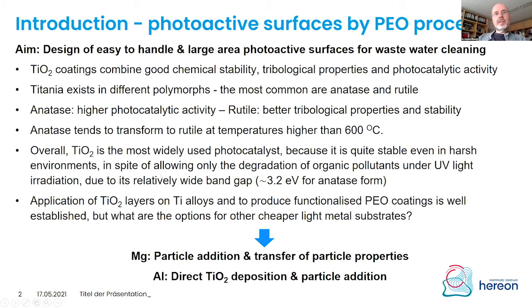So overall, one can say that titanium dioxide is probably the most widely used photocatalyst, because it is really quite stable even in harsh environments. In spite of that, on the negative side, we have to consider that the band gap of the titanium dioxide is relatively high, so we can only use UV light irradiation. But this we will address definitely in other research, which I will not talk about today, because you can also, by adding additives into the PEO process, try to reduce this band gap. But this is not the topic of today's presentation.